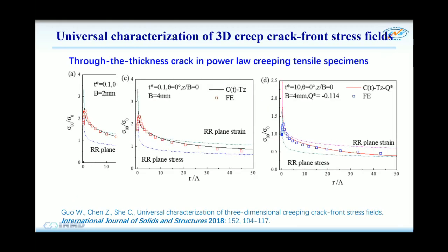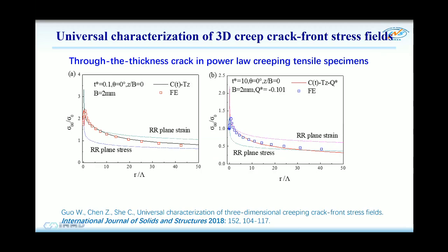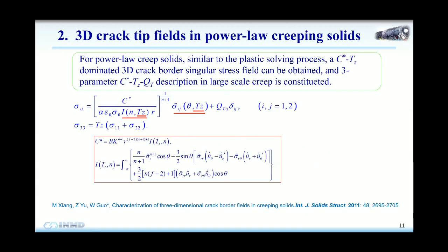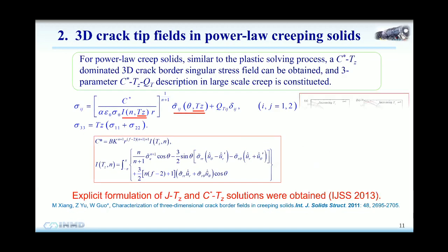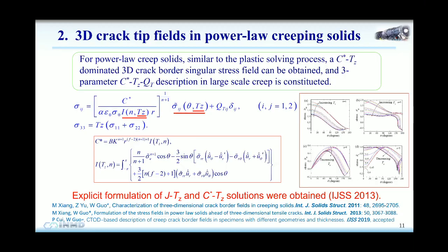You see, this is a different strain, and this is equivalent strain. And all these curves from plane strain to plane stress, you see the change is so significant. So the three-dimensional effect, the TZ effect, is very, very important.